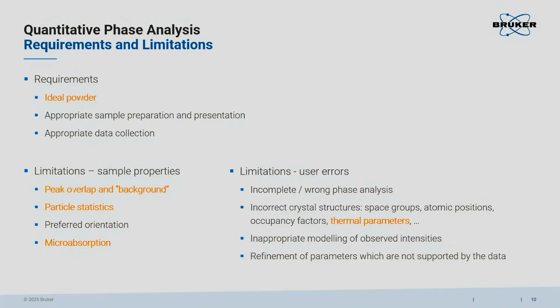There's a couple of limitations I would like to highlight. Peak overlap and background, particle statistics, preferred orientation we discussed yesterday, and microabsorption. And I forgot to mention, all the topics which are highlighted here in yellow I want to focus on. So this is the selective overview I want to give. There are also user errors, incomplete or wrong phase analysis, of course, incorrect crystal structures, space groups, atomic positions, occupancy factors. It happens more often than many people believe, and also thermal parameters, or Debye-Waller factors, as they are also called. I prefer thermal parameters.